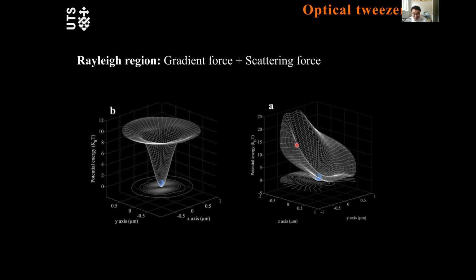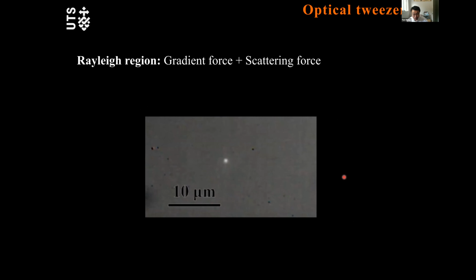Yeah, so nanoscale trapping is a really interesting one. If the particle is really small, it is basically within the Rayleigh range, and then you have the gradient force and the scattering force. If your scattering is really strong, it will tilt your trapping potential, and the particle is really easy to push out along the laser propagation direction.